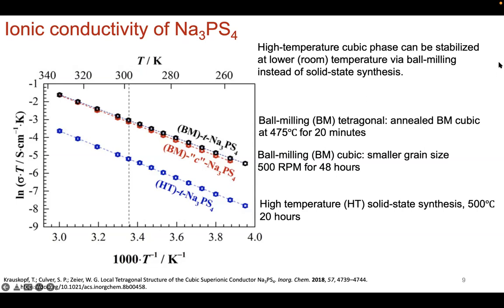You can also get smaller grain sizes by choosing an RPM, depending on if you're doing high energy ball mill or planetary ball mill, but 500 RPM is pretty in between, for about 48 hours. And when I say high temperature solid state synthesis, getting this tetragonal phase, it's 500 C for 20 hours. So all of these synthetic conditions are actually quite mild when it comes to solid state synthesis.